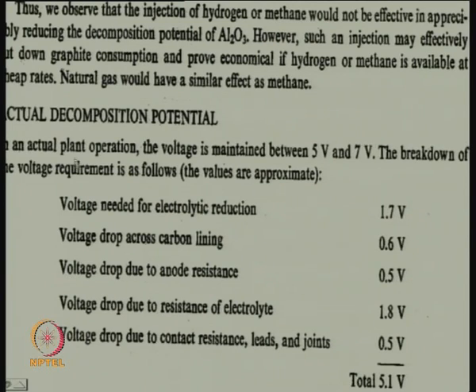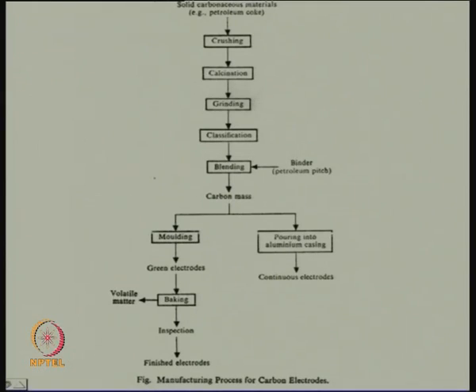It is good. So, the conclusion is that the injection of hydrogen or methane would not be effective in appreciably reducing the decomposition potential of alumina. However, such an injection may effectively cut down graphite consumption and prove economical if hydrogen or methane is available at cheap rates and there is technology to use them the way it is being suggested. The same thing goes with natural gas. So, these are trials people try and try to see what to do and what not to do, but it does not work. Now, let me wind up today's session by saying two other things.